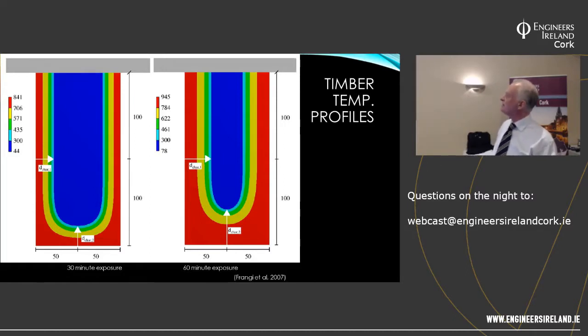At 60 minutes, again, it's up to 945 externally, which would be roundabout the ISO 834 curve. And it's 78 in the very middle, and you've a small piece of timber left, and it's 300 at the edge. So just to give you an idea about the insulation values of timber.